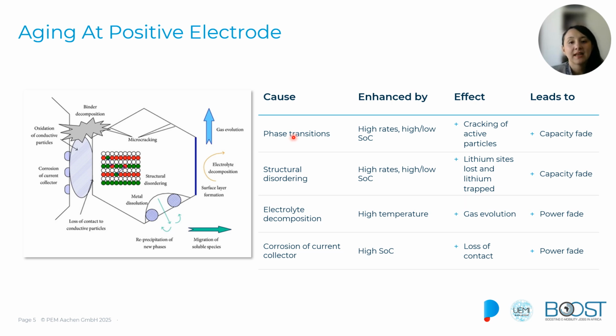Additionally, electrolyte decomposition at high temperatures and high state of charge will produce unwanted gases and further degradation of the performance of the battery. Another cause of aging at the positive electrode will be the corrosion of the current collectors, which can also occur over time, resulting in poor electrical connection, and also in power fade and reduced power output for our battery.